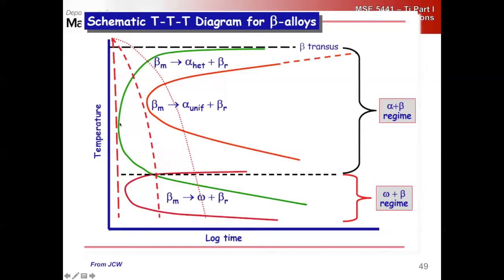Whereas going heterogeneously, we have enough alpha, so we can go a little faster. But ideally what we're trying to do is cool through this regime as quickly as possible to get down to the formation of athermal. And unfortunately, the nose, it's tucked back through here, so you have to play a lot of tricks with cooling rates and coming through.